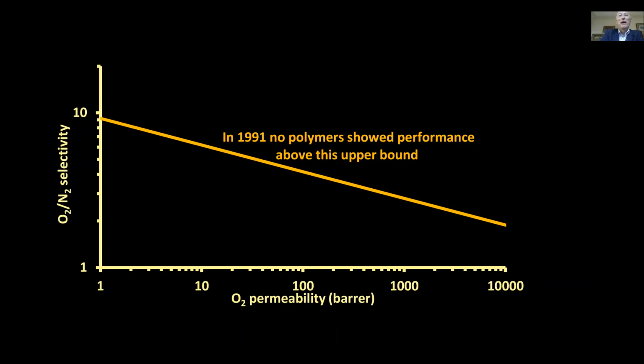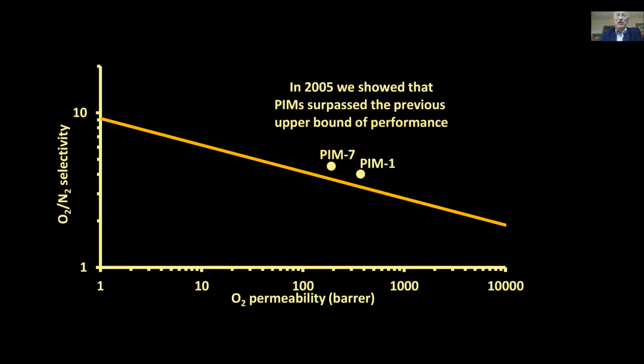Most polymers actually have quite low permeability. There are only a few that are very permeable over on the right-hand side of that plot, and they tend to be low selectivity. Now, in 2005, in collaboration with some researchers in Germany, we published the first gas separation data on the polymers that we refer to as PIMs. There's PIM-1, and also we looked at another PIM at the time that we called PIM-7. And we demonstrated that these polymers, as well as being much more permeable than the vast majority of other polymers, also broke that upper bound.